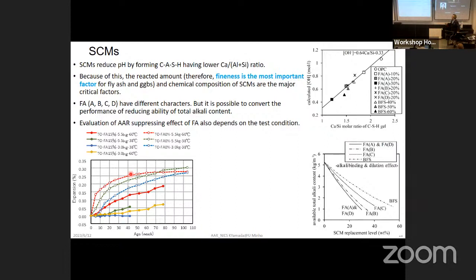But the important point is the pH of the pore solution. The pH of the pore solution can be calculated from the calcium silicon ratio of C-S-H. This value can be calculated assuming the chemical composition of the glass and the reaction degree. We can calculate this value. Then, of course, we have to think about the sodium concentration. It is possible for material science, I think.